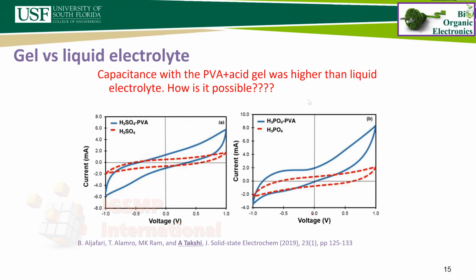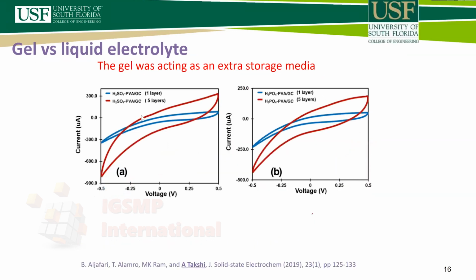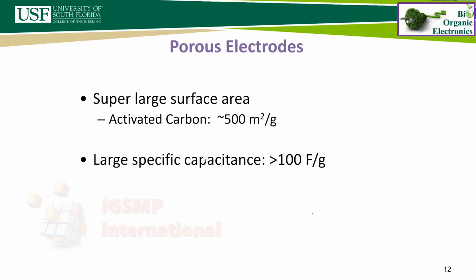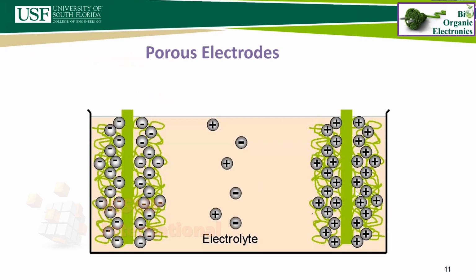If you're familiar with the concept of the diffusion of ions in solution, you may expect that liquid electrolytes would perform much better than gel electrolytes. But our results showed the opposite. We also looked at the case where we made the supercapacitors with the gel electrolyte of 1 layer or 5 layers, so technically increasing the thickness of the gel 5 times, and the capacitance increased. So one more time, I would like to go back to this, saying that technically in this design, the spacing between the 2 electrodes should not make any difference. But with the gel, we noticed that it actually makes some difference. So that brought up a question that perhaps something is happening inside the volume of the gel that needed to be further investigated.